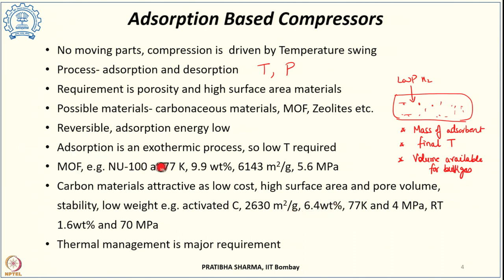Since adsorption is an exothermic process, the heat released during adsorption needs to be removed from the storage tank. A lot of thermal management is required — not only for the heat generated during the process, but also heat must be supplied for desorption. If the heat produced during adsorption is not removed, the temperature of the bed increases, which reduces the rate of adsorption and degrades efficiency.